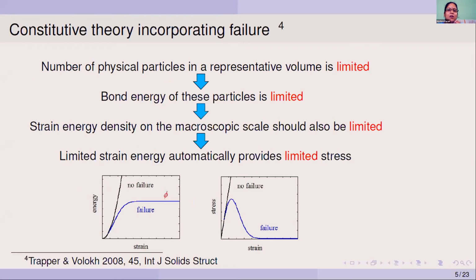And this idea of softening hyperelasticity is essentially an extension of the description for two particle separation to a larger number of particles in a representative volume of the continuum. And this number of physical particles in the representative volume is limited. So the average bond energy of these particles is limited. Consequently, the strain energy density on the macroscopic scale should also be limited.